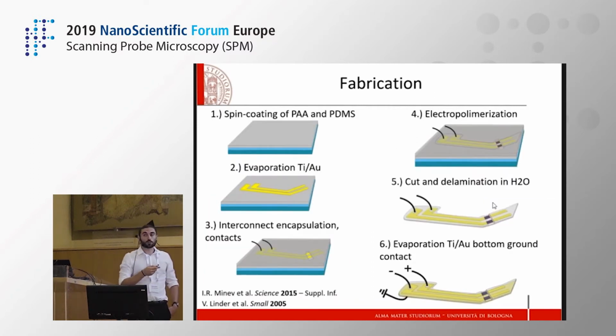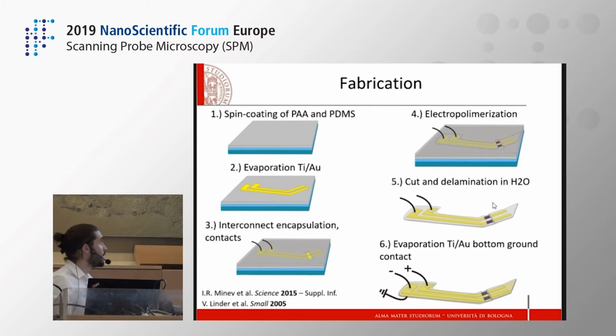Here is the fabrication procedure, which is based on several steps, but is quite an easy procedure that can be done outside of a clean room, fabricating tens of electrodes in 3 to 4 days. And the last step is an evaporation of titanium and gold on the bottom of our electrode in order to shield the signal from external noise.